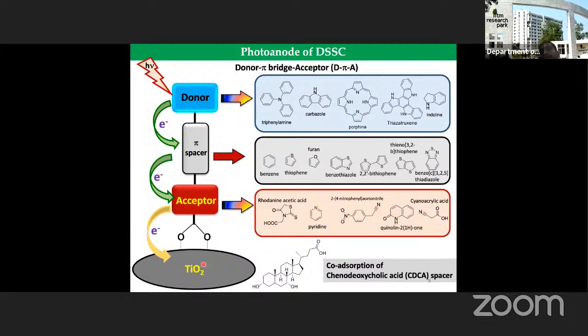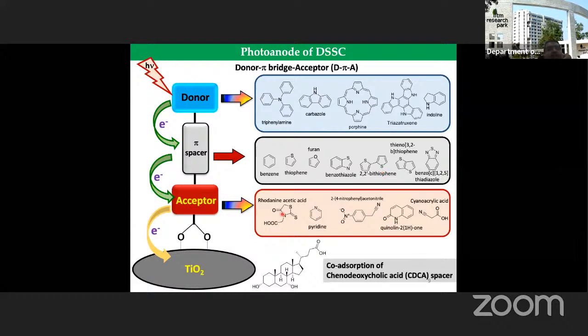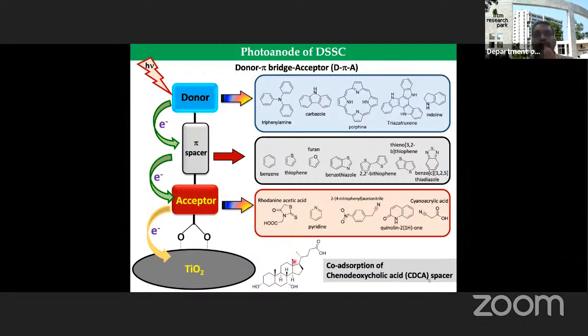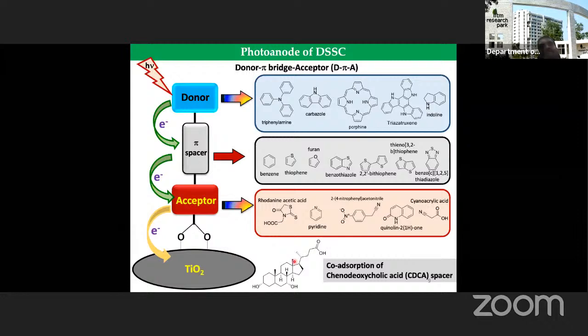If it has to land in the conduction band of titanium dioxide, the excited level at which the electron is present should be above the conduction band of the titanium dioxide. Otherwise, injection will not be feasible, right? So the donors are of this kind: triphenylamine, carbazole, porphyrin, triazatruxene, indoline, right? The spacers can be any pi spacer like benzene, thiophene, furan, and so on, right? Acceptors, the well-known acceptor is cyanoacrylic acid. There are other acceptors like rhodanine, pyridine, okay? So these types of acceptors are present. Generally in DSSC, people also use one more compound called chenodeoxycholic acid, abbreviated as CDCA.